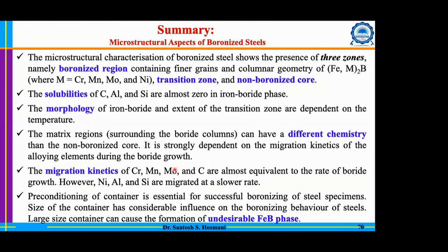And the solubility of elements like carbon, aluminum, silicon is essentially zero in iron boride. That means they are entirely rejected. And the morphology of this iron boride is very much dependent on process parameters like temperature and the migration kinetics of these elements. That is what we have seen here. Because of that, the chemistry of your matrix will be entirely different during the growth of boronizing because of accumulation of certain elements there.